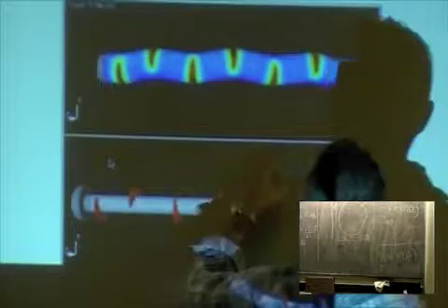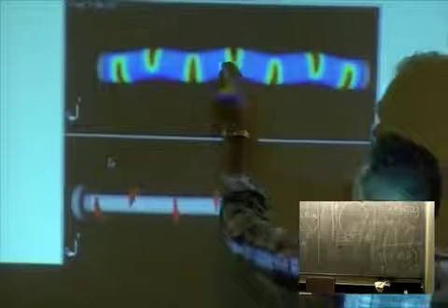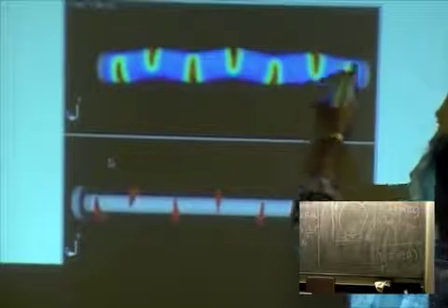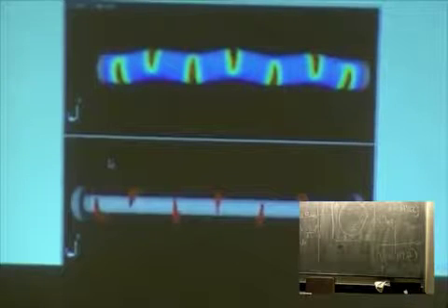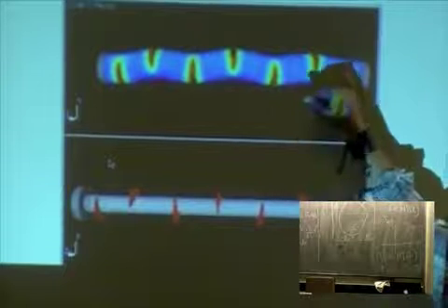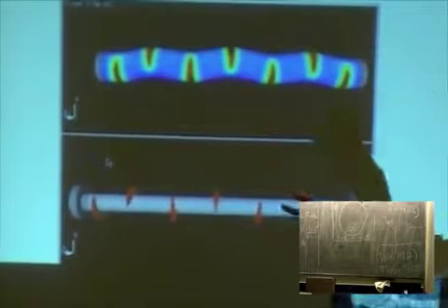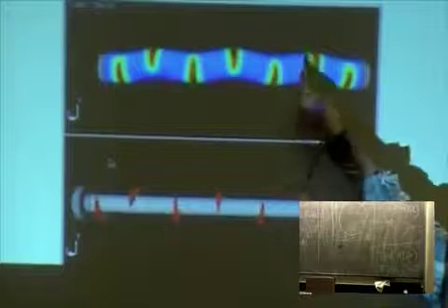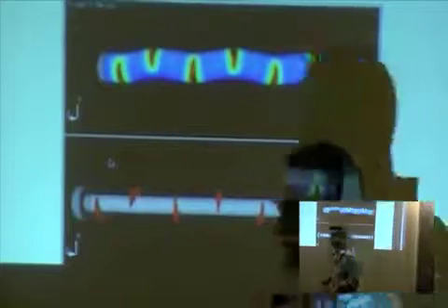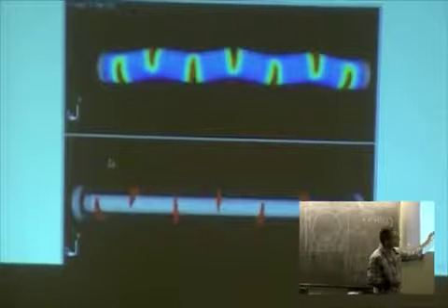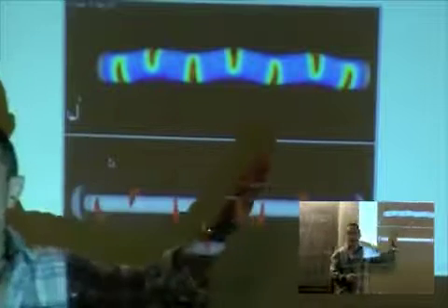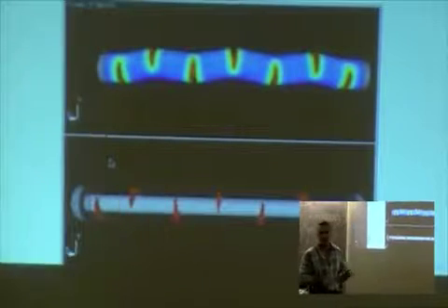I don't know if you can see that, but since it's bonded here, over there, there is bending of the core. The core is unbreakable, but it bends. It's bending because of the difference between elasticities of the core and the bonding. So the core does this, and then you have this crack. And this is something which is observed. Exactly, this kind of transverse cracking is observed. So once again, it's qualitative.